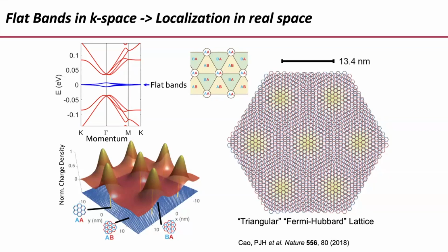So you end up schematically with something where twisted bilayer graphene becomes this solid, where you have some regions of AA stacking separated by about 13 nanometers where the electrons like to be. And this is sort of going to be a little bit of an analog of a triangular Fermi-Hubbard lattice in cold atoms language, okay? Except that I have a lot of quotes here. In reality, this thing is honeycomb because AB and BA is not the same. And it's not really a Fermi-Hubbard lattice because these electronic properties of twisted bilayer graphene have a special topological structure that prevents a direct mapping to a vanilla Fermi-Hubbard lattice of the cold atoms type, okay?